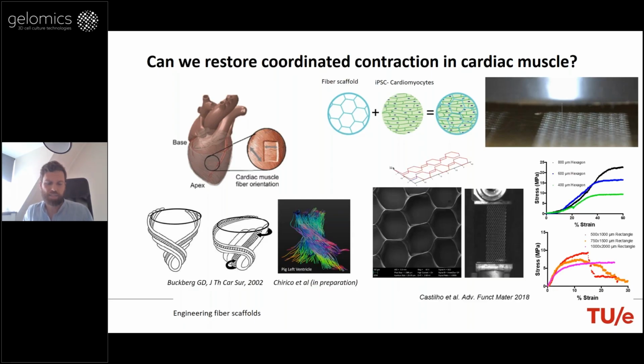The reason for looking at these hexagons is that in this case we were looking at polycaprolactone, which is an FDA-approved polymer that has all the benefits in terms of later clinical translation, but it suffers from some mechanical pitfalls. At large deformations, typically above 5%, this bulk material basically undergoes permanent deformation, which means that if you cyclically stretch it, it will permanently deform, which is, as you can envision, something that you don't desire as a material to replace a piece of your myocardium tissue.